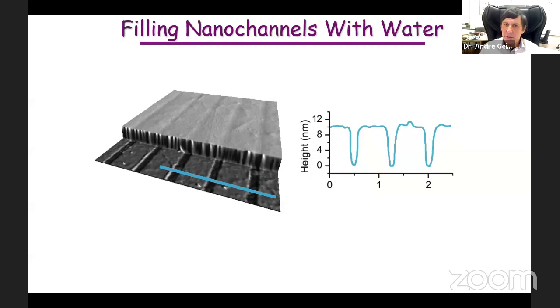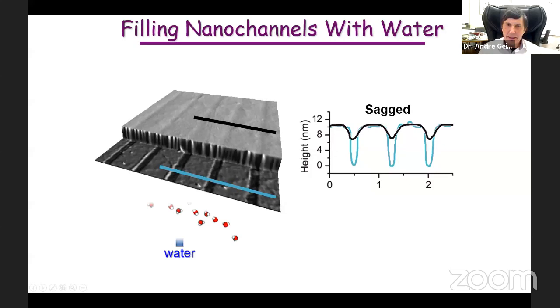This is an AFM image. This is outside the capillaries, our spacers, in this case 9 nanometers thick, very thick channels. There is a top crystal, and you see it's a little bit sagged inside. And if we make a scan here, we see that the sagging is about, okay, 1-2 nanometers. Then we add water, and as water is added, we see that the channels are straight, indicating that water was inside. And then we do something else.